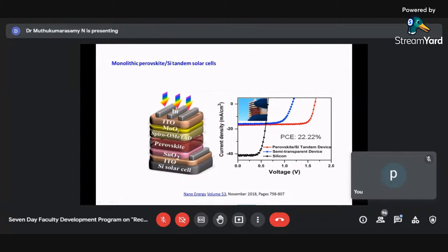Over the silicon solar cell, you can go for ITO, SnO2, perovskite, then spiro, molybdenum oxide. Working with molybdenum oxide, you have to be careful because when you anneal it, you'll have some issues in the interfacial region. Then also with ITO. Then they have taken indium contact and they have reported an efficiency of 22.2%. This is a tandem solar cell, that is a silicon solar cell and a perovskite solar cell connected in series. So they were able to report an efficiency of 22%.